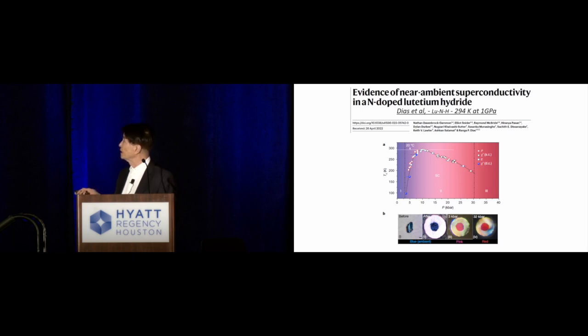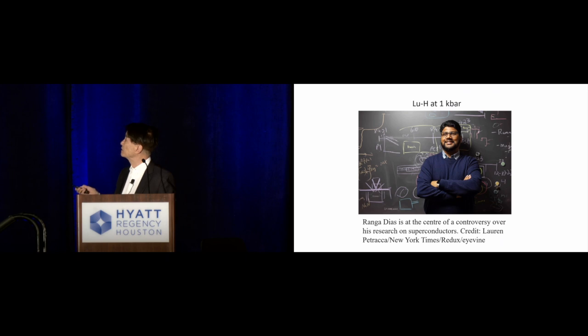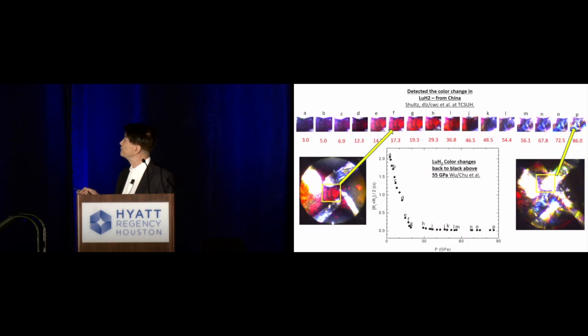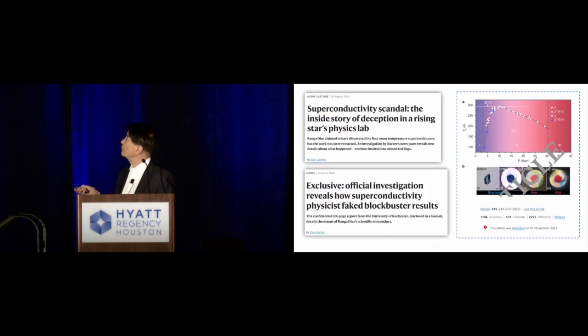And you can see under pressure, the sample can change color from black all the way to red. Of course, we also followed these things. And this is the person, Ranga Dias, okay? We reproduced the color change of the sample under pressure, but we could not find any superconductivity happening in this material. So finally, people call it the superconductivity scandal.